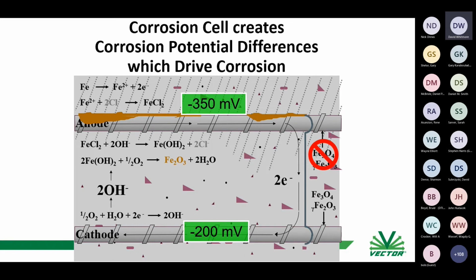In this very simple graphic, I've illustrated a top mat of steel and a bottom mat of steel in a bridge deck, which is very typical. You know, you have chloride contaminated steel at the top, not chloride contaminated steel at the bottom. You'll have a macrocell current that flows from the top steel to the bottom steel, like you see here. You will have the exact same thing happening on that bridge deck between the top of the bar and the bottom of the top bar, typically because there's a difference in the chloride concentration, even in that 1/2 inch or 3/4 inch distance, right?